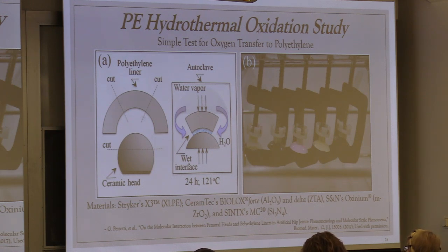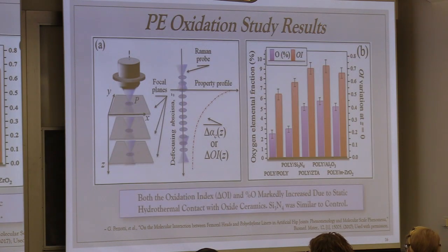So this was a very simple experiment. We just took a polyethylene liner, a very advanced polyethylene liner, and we cut heads of 4 different materials: zirconia toughened alumina, an alumina, a zirconia, and silicon nitride. And then we had a standard in there, which was polyethylene on polyethylene. And then we just put it in the autoclave for 24 hours at 121 degrees C to see, is there going to be any sort of physical or chemical changes that occur in the polyethylene during this particular short duration test? And that was examined by using XPS and Raman spectroscopy. I'll just show you the Raman spectroscopy results.